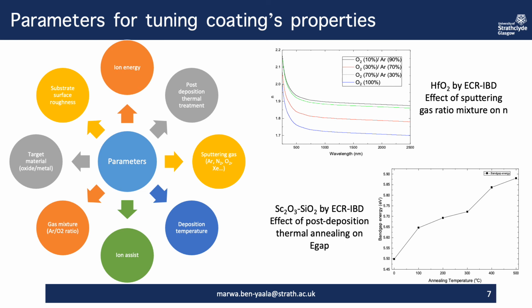And here I'm presenting two examples of deposition parameters impacting film properties. The first one on the top here, you can see the change of the refractive index of Hafnia films with the oxygen to argon ratio, so both sputtering gases that are injected through the sources. And in this figure down here is shown the variation of the band gap of Scandia films, Scandia dot silica, with the annealing temperature.